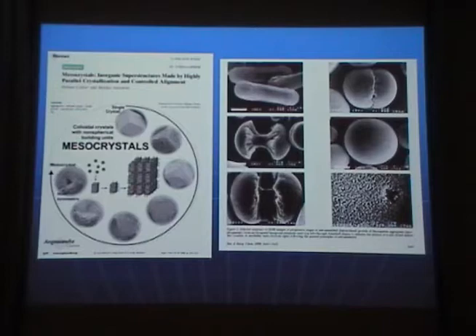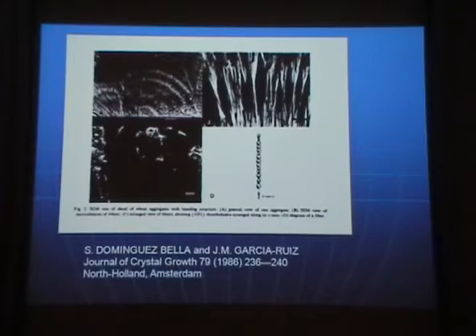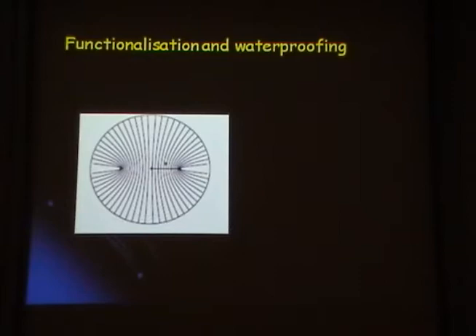So the idea is that they grow something like this, that they grow like sheaf of wheat. So they are little crystals that bump on each other, and then they sort of form like sheaf of wheat. And then they sort of fill those little bits and pieces, and all of a sudden, bingo, you have a spherical crystal. So that's how it happens. But how come that it's still so birefringent? Well, this is how they're formed. So they sort of stuck on each other, and then eventually they form this sheaf of wheat, which has a predominant, very well-defined optic axis. Okay, so this is how the crystal looks like.